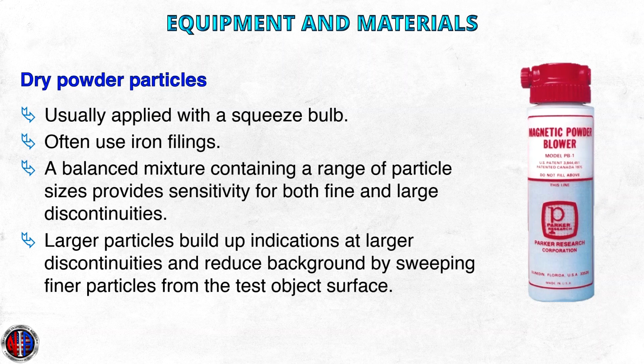Dry powder particles. A carefully controlled and balanced mixture containing a range of particle sizes provides sensitivity for both fine and large discontinuities without disruptive backgrounds. The smaller particles provide sensitivity and mobility, while larger particles serve a twofold purpose in building up indications at larger discontinuities and reducing background by sweeping finer particles from the test object surface.